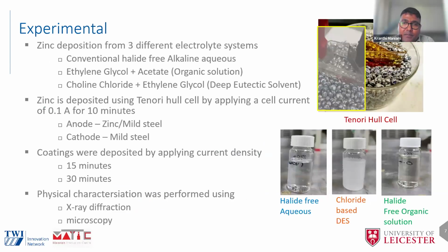And to understand this, first what I've done is I have taken a conventional halide-free alkaline aqueous system, cyanide-free as well, and I've taken an organic solution containing glycol plus acetate, and a popularly known deep eutectic solvent, which is choline chloride plus ethylene glycol. It is a deep eutectic solvent formed by mixing choline chloride and ethylene glycol in different ratios.